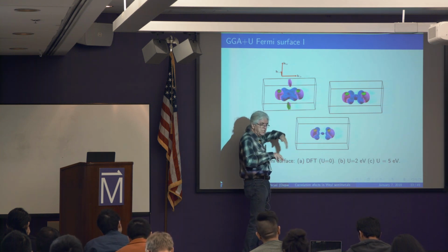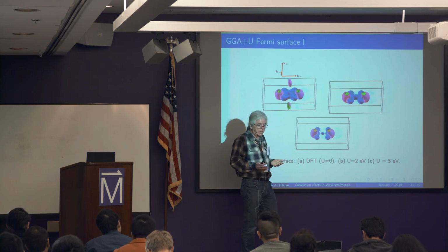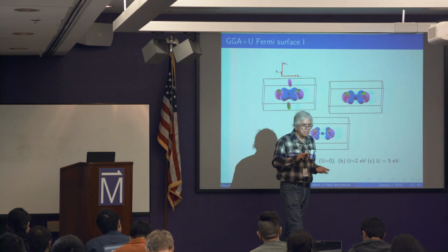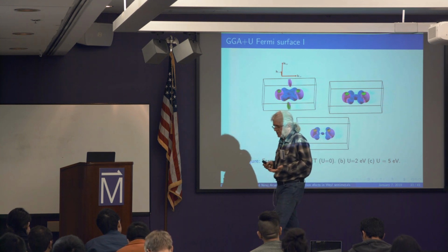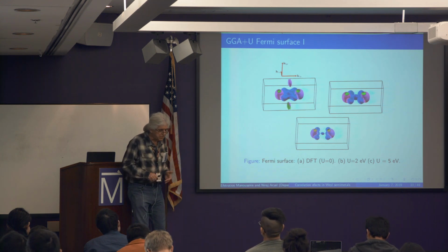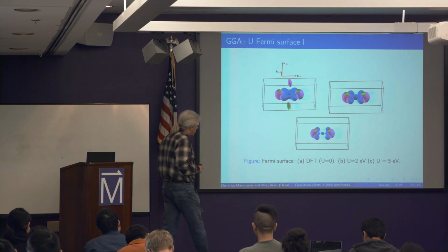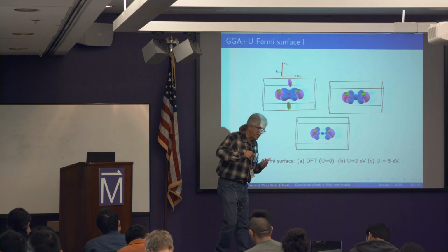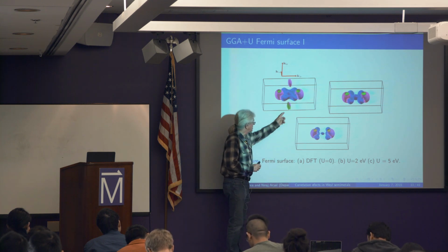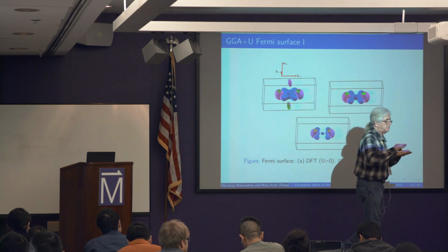Plus, these pockets must be lurking near the Fermi level. Now they are inside, they're gone, but they are not too far away. They are maybe a couple of meV below the Fermi level. So with a couple of meV or 1 meV, you can have very anisotropic response, because any magnetic field is going to maybe pop out again, re-emerge these pockets, which are only in this direction.